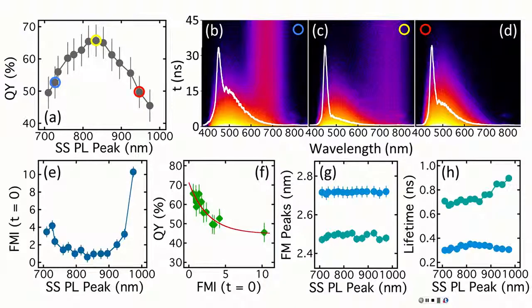We can't completely control it. Is it carbons or hydrogens? NREL says it's surface states. NREL says it's mixing, but they don't say where it comes from. But they say that they don't have any passivation issues. Now, what is your passivating ligand? 1-dodecene. So it's many carbons, a linear chain? Dodecene, yeah. 10 carbons? 12. 12, okay. Do you have results for something like benzene rings? No, this is all we got.